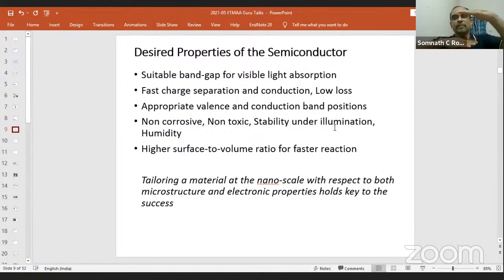Then you should have appropriate valence and conduction band positions. Here also it is important, depending on what kind of redox, that is reduction and oxidation reactions, you are looking at. It could be water splitting, it could be other chemical reactions also. You should have a proper position of your conduction band so that you can get the electron from that level, and a proper position of the valence band so that you can get the hole, or the vacancy, at a desired energy. So here lies the additional challenge: not only is the gap important, but where this edge lies and where that edge lies are also important.